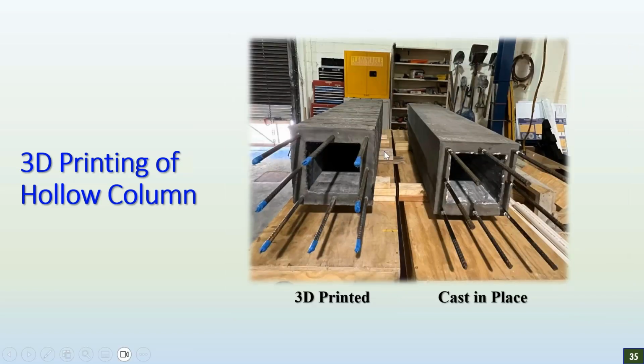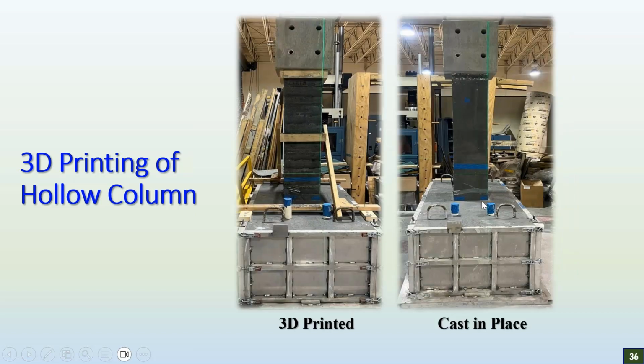So again, to see the behavior of this hollow column against cyclic loading test, a similar cast-in-place specimen was constructed by using the same reinforcement ratio, and both of them are placed side by side so we can see the cross section of both of these columns. So these are the final specimens for the cyclic loading testing, and both hollow columns were fabricated. The footing was constructed by using a pocket connection with the UHPC, and the actuators were installed on top to apply the axial and cyclic loading.